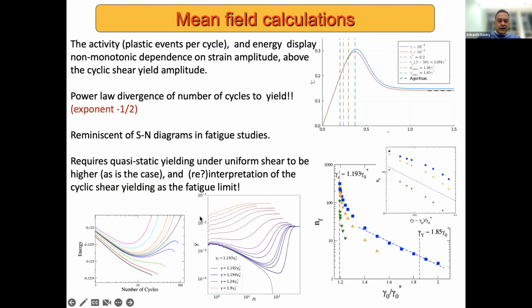But here is the interesting thing. If one looks at the activity as a function of the number of cycles at different applied strain amplitudes, there is a range of amplitudes over which this activity is non-monotonic. So it begins to decrease. And if you're below the cyclic shear yielding point, it goes all the way to 0. But if you're slightly above, it decreases very much like what would happen below the yielding point. But then at some point, it kicks up and goes to a finite value. And this upturn signals the failure event in this system.